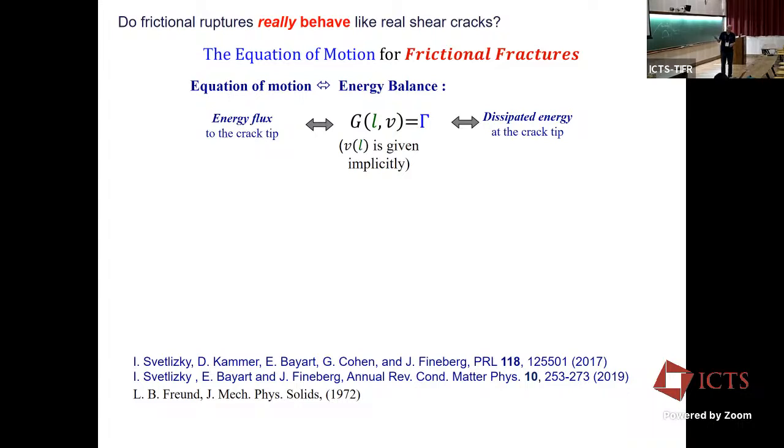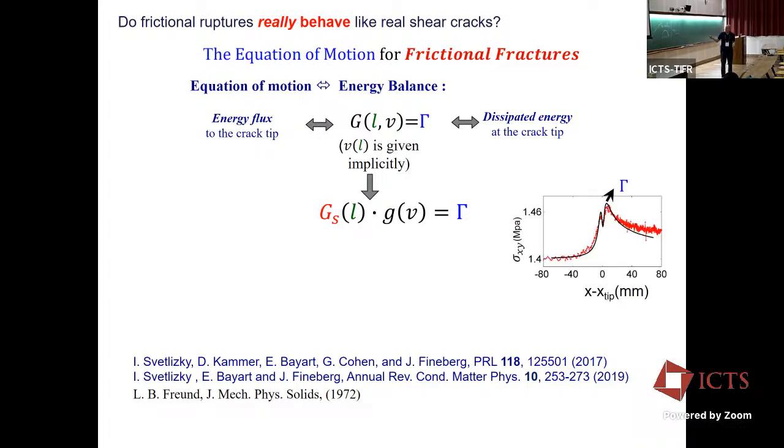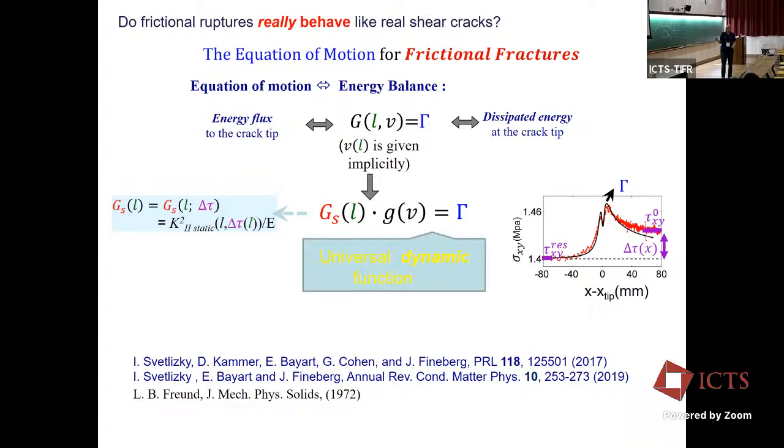Okay, this is energy balance again. So the energy flowing into the tip of the crack is equal to the energy cost, this gamma. Now, for large systems, there's a miracle of nature that this breaks down into this static stress intensity factor that we just calculated with the stresses. This is where we got our criterion for crack arrest, times some universal function. This we measure, of course. Okay, this is the static thing that we just talked about, where we measured the K static, and K squared over the Young's modulus is equal to this thing. And it's a function of the virtual length of the crack. And this is a universal function,